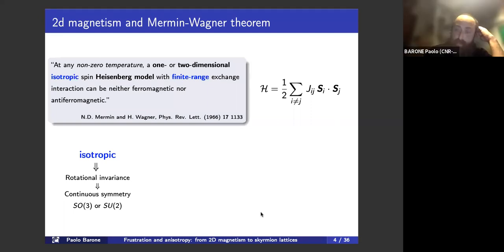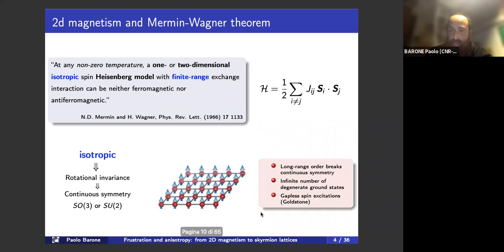And the point is that if we assume that this magnetic system establishes a long-range order, this long-range order breaks this continuous symmetry. And this has two consequences. The first is that we have an infinite number of distinguishable states, obtained by any arbitrary rotation of the magnetization axis, which are degenerate. And the other thing, which comes simply from the fact that we are breaking a continuous symmetry, is that we expect gapless spin excitations.